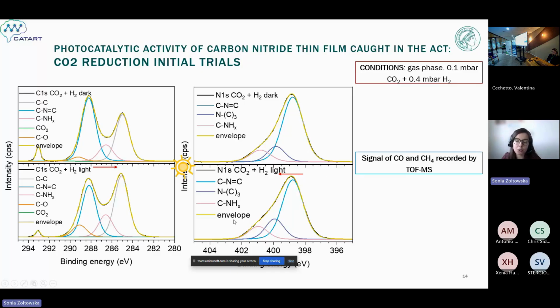And on the other hand, here we also observe a small shift of the N level features towards higher binding energies, and we assume that the photo-generated holes are localized on the nitrogen species, and they are of course shifting the features towards higher binding energies.